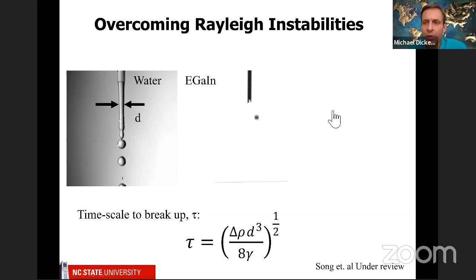I wanted to draw a parallel, one of the reasons this is so fascinating. If you take water and pump it out of a hose or out of a faucet, you'll know from experience that it will form a cylinder, but it will quickly break up into droplets. That is called a Rayleigh-Plateau instability. It's driven by minimization of surface energy. This is really just a scaling argument, so don't get too caught up in the details, but the time to break up depends on the diameter, D. If you want it to break up faster, you make D really small. And if you want it to break up into droplets quickly, you want to use something with a high surface tension. If you do this calculation for water, this stream should break up in about 0.01 seconds, 10 milliseconds. So these streams are very unstable. Imagine now if you switch over to liquid metal, and the diameter of this nozzle is about 100 microns.